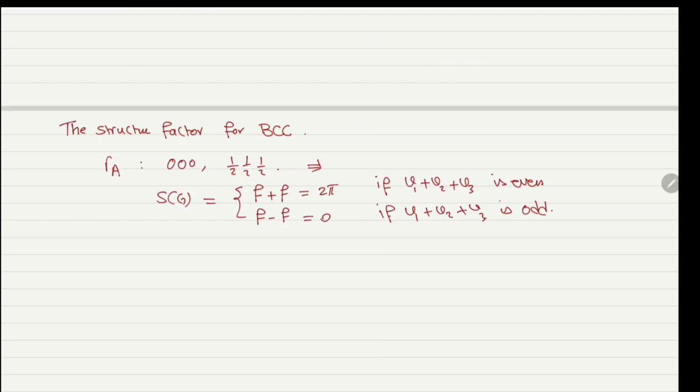This means that there's no diffraction when V1 plus V2 plus V3 is odd. For instance, 1, 1, 1, there is no diffraction from that plane.